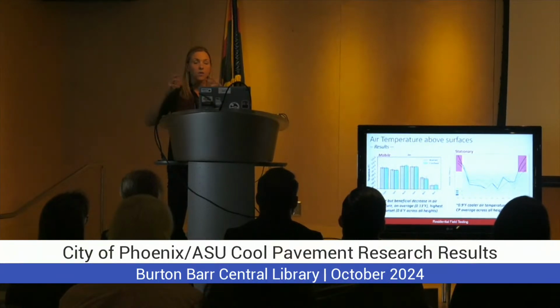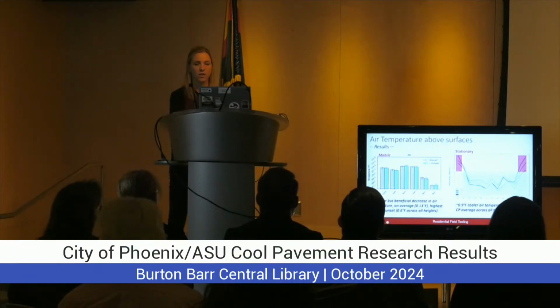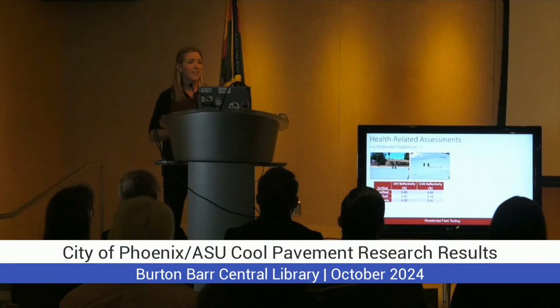And then we also have to recognize that at certain times of the day, we did see this flip that we're looking into, but it might have something to do with the fact that the cool seal part was very smooth and the asphalt part, traditional asphalt, was more of a chip, so it was rougher, and so we think that resulted in it transferring heat to the environment a bit quicker after sunset, so in this area here. It's an interesting result nonetheless.